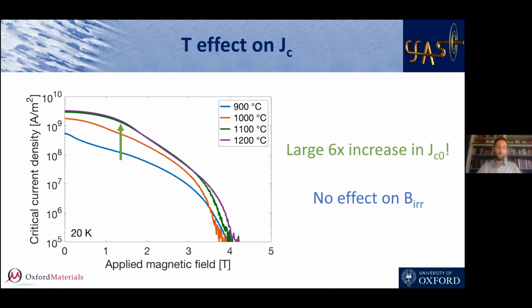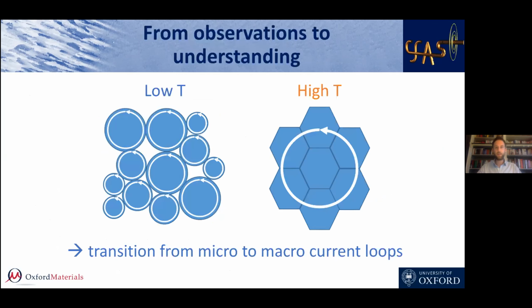And so the next step obviously was to understand why that would be the case. It's actually quite counterintuitive that you have a better JC when in fact you have coarsening. And this can be explained quite simply, because what we measure is not the intrinsic JC, but rather a macroscopic JC, which depends heavily on how connected your microstructure is. So in the low temperature sample, we can see on that schematic microstructure that we had small current loops restricted to individual particles because the connectivity was quite poor. And then on the right, for higher temperature, and that's also to put in perspective with what we've seen in the SEM images, we have a much more connected microstructure. So there we have macro current loops. And because we extract JC from macroscopic magnetization measurements, it appears that obviously the JC is higher.